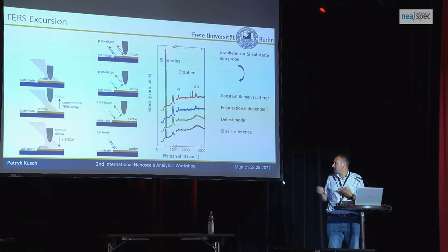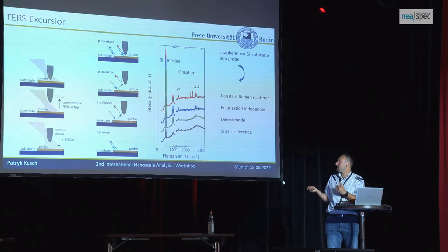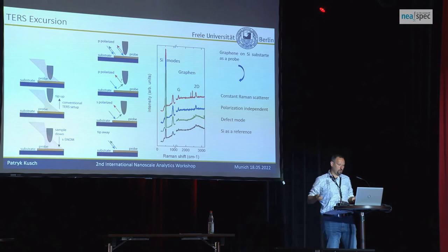To get rid of this effect, we change to S-polarized light to modify the near-field, and then we see the signal really decreasing. So it may really be related to a mirror effect or the near-field at the tip that enhances the signal. The ultimate approach was to remove the tip completely, drive the sample back into the focus, and then observe the difference between tip-up and tip-down.